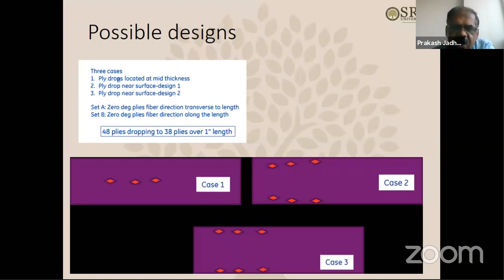Then there are two more designs, as you can see. Here the ply drops are located near the surface, but they are in series like this. And here the ply drops are located near the surface, but they are not in series. They are in a zigzag arrangement like this. Okay, so all these cases that we tried, and these three cases were also repeated for fiber direction transverse to the length and fiber direction along the length. Okay, like fibers are oriented along the length and across the length like this.